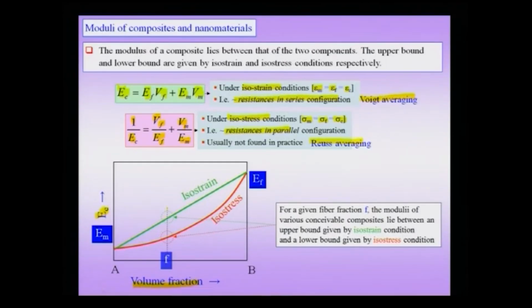Suppose I take any given volume fraction f, just for the sake I will call this f1 here. Then I have an upper bound given by the isostrain condition, which is nothing but the Voigt averaging, and I have a lower bound given by the isostress condition, which is the Reuss averaging. Therefore, the modulus of the composite is going to lie between the upper and lower bound.